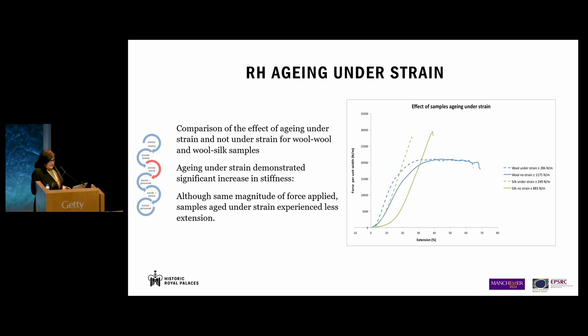So tensile testing results of the aged samples under strain compared to the ones which were placed on the rack are shown on this graph. Blue indicates samples with wool weft and green samples with silk. The dotted lines represent the results of the samples that aged under strain, and they demonstrate clearly that they experience a significant increase in stiffness. This is an important observation, as many tapestry collections are hanging under the strain of their own weight for a long period of time.